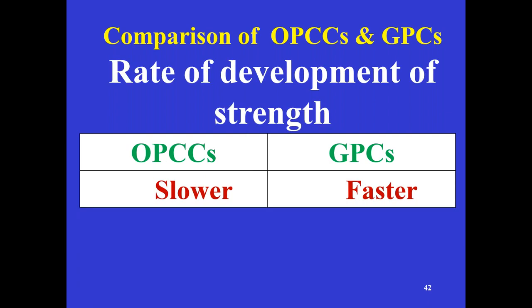Okay, now development of strength. OPC can also get the strength level you want with water curing. But because geopolymerization is possible here, and polymerization reactions are managed easily and faster, generally we can say geopolymer concretes will develop strength faster. And most of the strength may be obtained in a short time because the polymerization reaction would be over by 1 week or 2 weeks or 3 weeks, whereas a cement reaction will continue forever. After 3 months also it will continue. After 1 year, 2 years, the reaction is continuing. Whereas geopolymer, most of the time it is over by two weeks or 3 weeks or 1 month, like that.